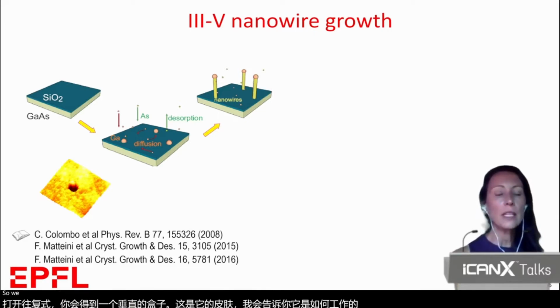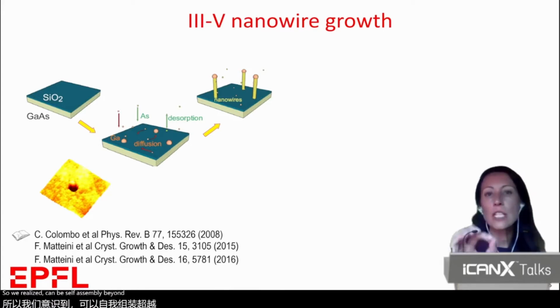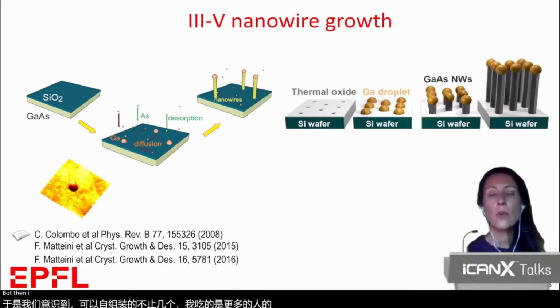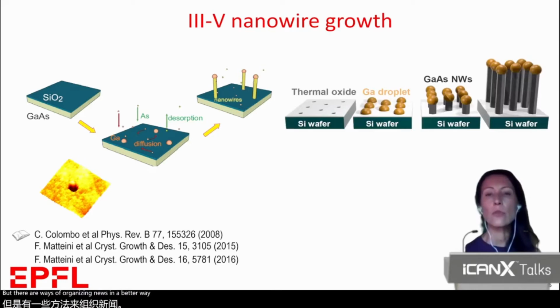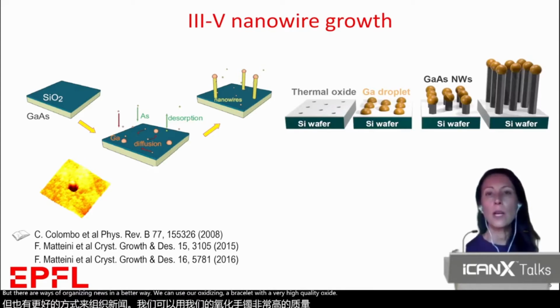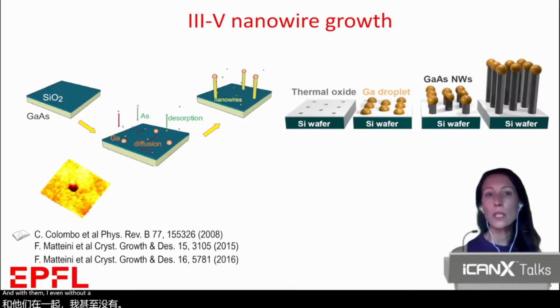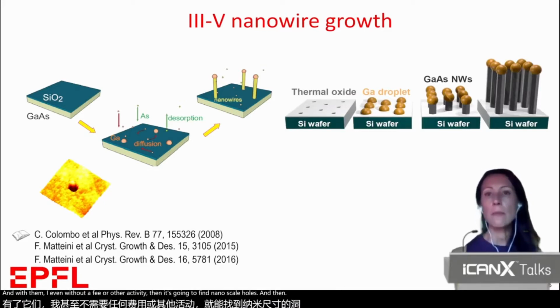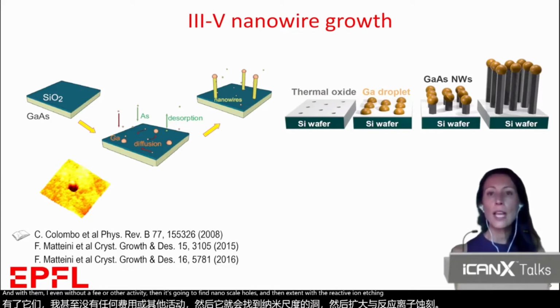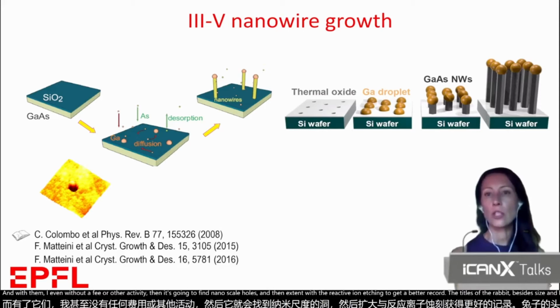So in self-assembly, we all rely on very small pinholes. But there are ways of organizing this in a better way. We can use an oxidized silicon wafer with a very high quality oxide. And with e-beam lithography or other nanopatterning techniques, we can define nanoscale holes and then etch them with reactive ion etching to get very well-ordered holes of very precise size and location on a substrate.